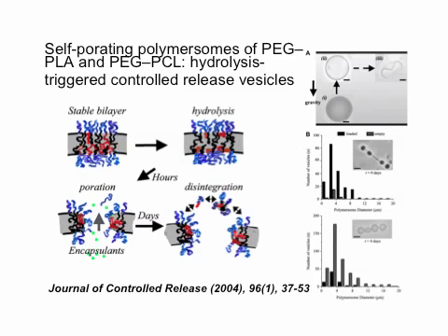In this example here, you have a bilayer that's made out of two components. One part is polylactic acid, and one part is polycaprolactone, and one of the two components hydrolyzes way quicker than the other one. So you start to rupture the structure, you get a permeable vesicle system, and then stuff can disintegrate, and you can get gradual or controlled release, depending on your conditions. You can do this enzymatically, or via a pH trigger.